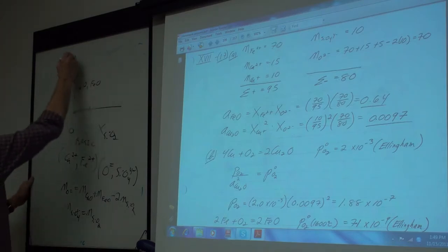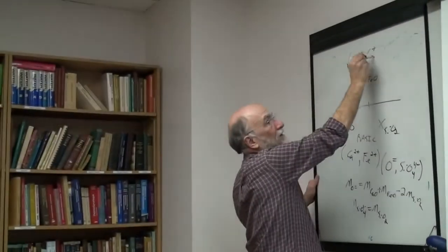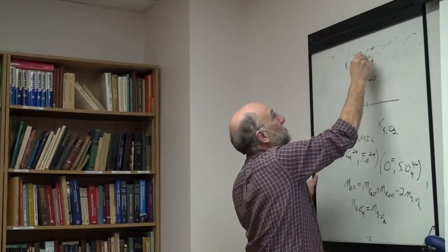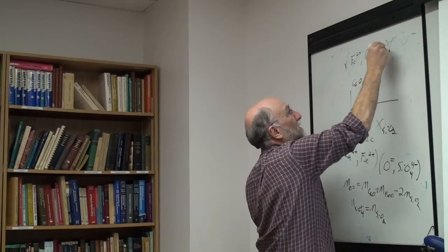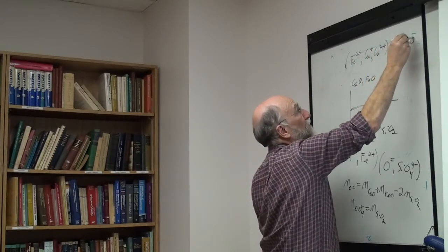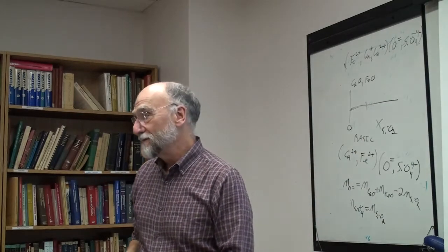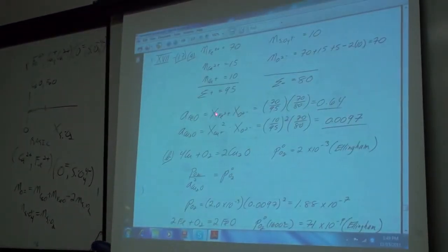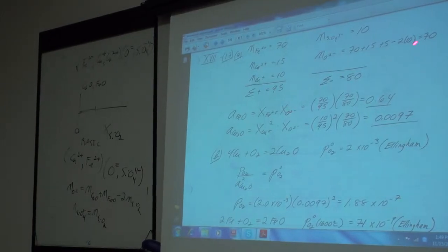Right, your model. The model for this solution is iron, copper, calcium, and over here you have oxygen ions and this SiO4 with four minuses, so we do our mass balance. The activity of FeO then is the product of the site fractions. The site fraction of iron is 70 over 95. The site fraction of oxygen is 70 over 80.